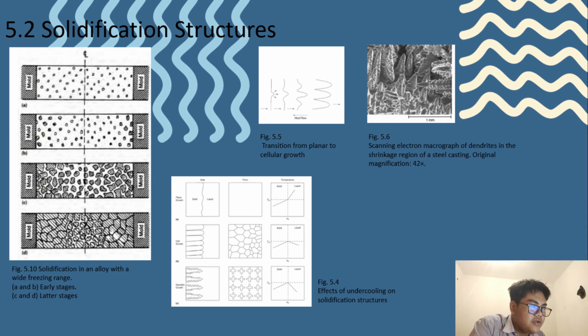When the liquid ahead of the solid-liquid interface has a positive temperature gradient, heat is removed from the liquid by conduction through the growing solid. Because the temperature gradient is linear and uniformly perpendicular to the interface, a smooth interface is maintained, and the growth is planar into the liquid. When there is a temperature inversion and the temperature decreases ahead of the solid-liquid interface, then either cellular or dendritic growth will occur. The difference between the two is a matter of degree. Small undercoolings tend to produce cellular growth, while large undercoolings tend to produce dendritic growth.